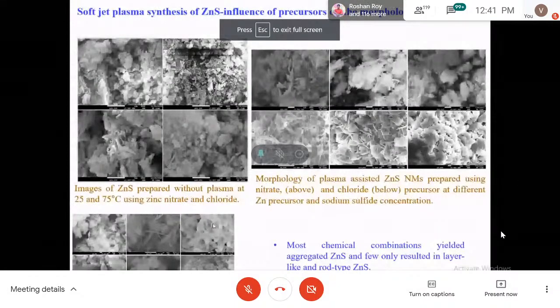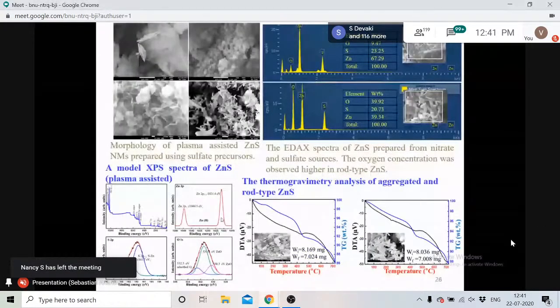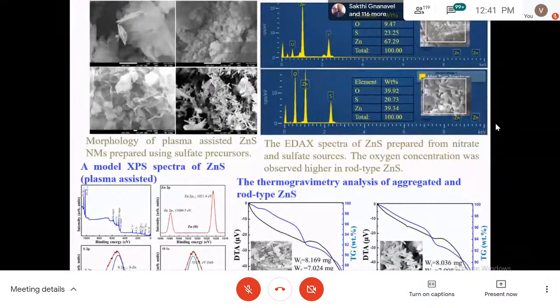So what happened? Here you can see, when we use zinc chloride, we get a one-dimensional structure also. This is one of the important findings when we use the same soft jet plasma. Here we used zinc sulfate as the precursor, and when changing the concentration, we get, you see, one-dimensional structure like zinc oxide. We get one-dimensional zinc sulfide in the presence of plasma. So without plasma, there is no possibility of a one-dimensional structure.